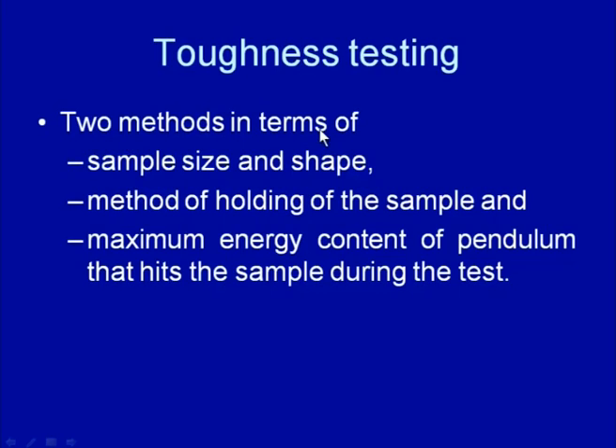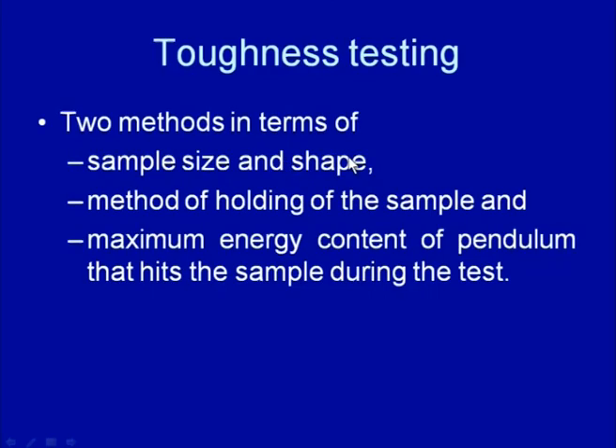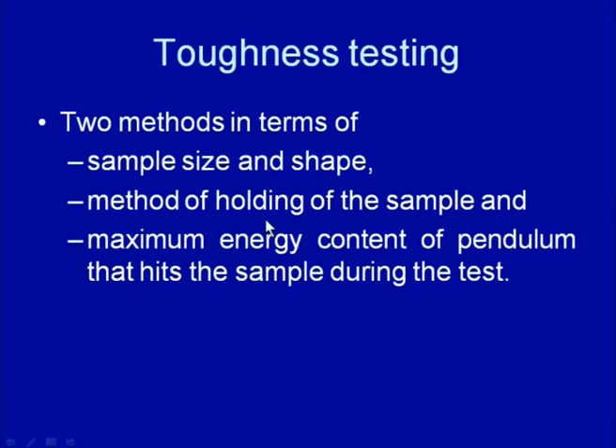In both the Izod and Charpy methods the same principle is used, where a pendulum is raised to a higher level and allowed to fall and strike the specimen to be tested, and the energy absorbed in the fracture process is recorded to see how tough the material is. But the placement of the specimen, the type of specimen, and the energy the pendulum has are different for the two methods, in terms of sample size and shape, the method of holding the sample, and the energy the pendulum contains before impacting the specimen.